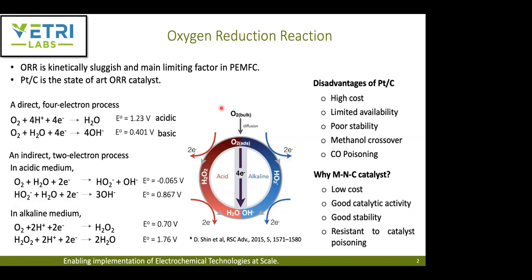So what is the problem with the state-of-the-art catalyst, and why are people working on alternative catalysts? We all know platinum is an expensive material, and its availability is very limited. It has very good catalytic activity, but suffers from poor stability when operated for longer cycles. Depending on the fuel cell in which ORR is employed, such as a direct methanol fuel cell, it suffers from methanol crossover. When methanol crosses over from the anode side, it can react on the cathode side and decrease the activity of your cathode catalyst. They are also susceptible to carbon monoxide poisoning.